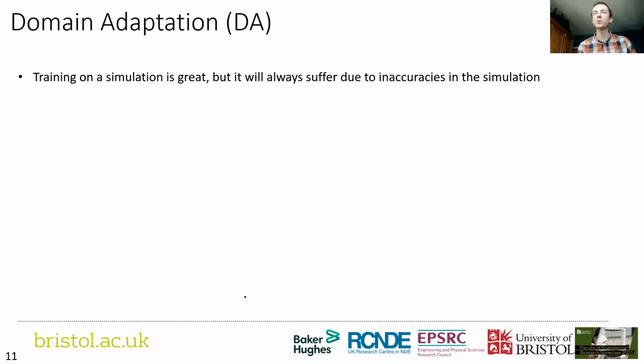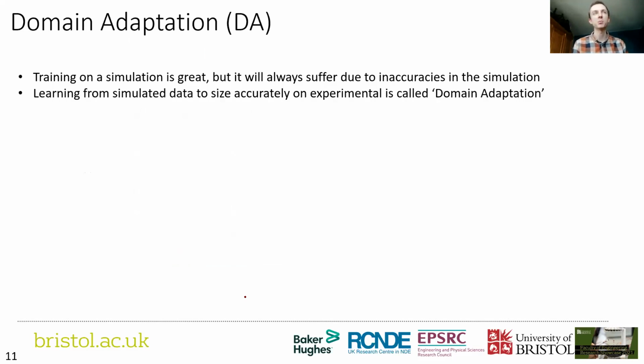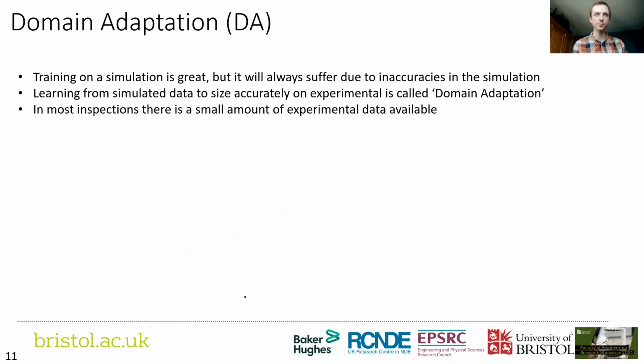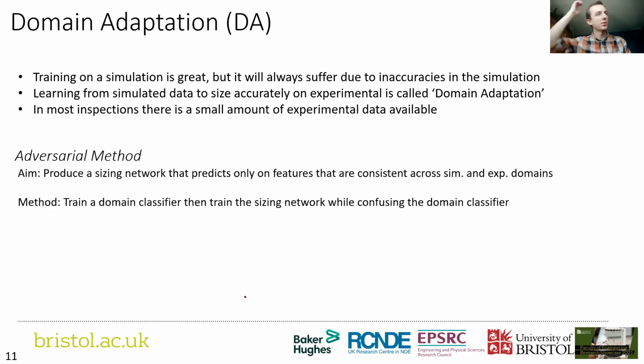And often you've got some experimental data hanging around, and you'd like to be able to use that in the training process. This is what's called the domain adaptation problem, where you're primarily learning on something that's very similar to your test set, but not quite the same. And you've got a little bit of true or target data available. As I say, you've normally got a little bit of experimental data available, and there's pretty much never enough to train a full deep learning network, but we'd like to be able to use it anyway. So the method I've had the most success with here is an adversarial one.